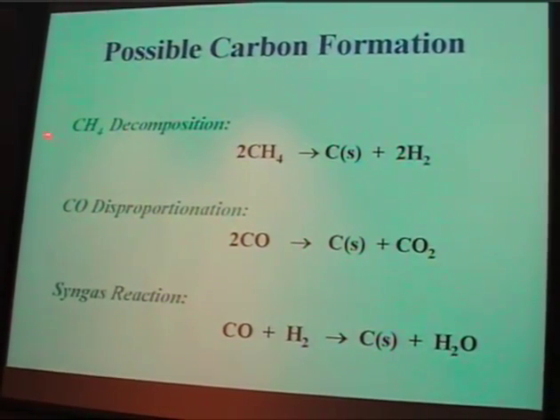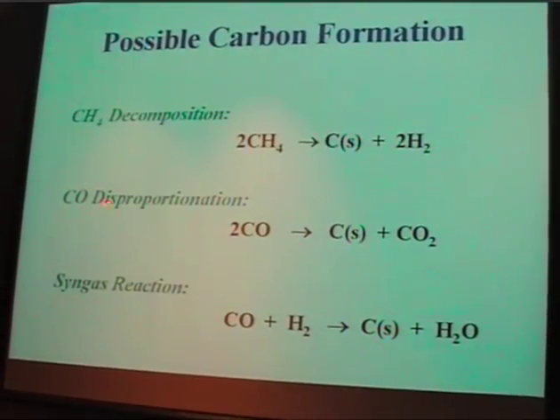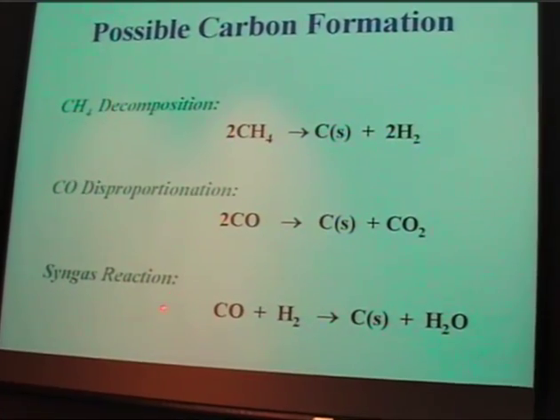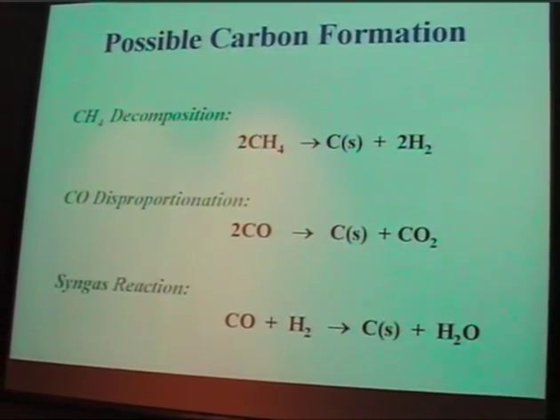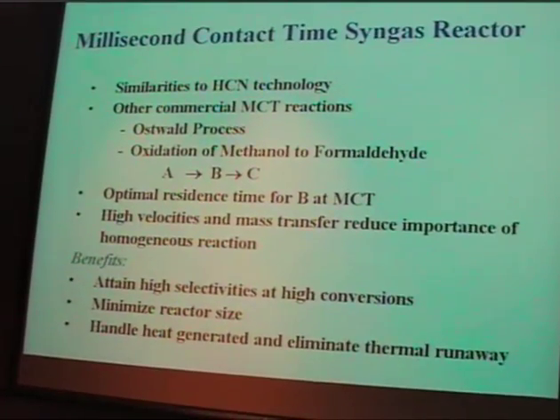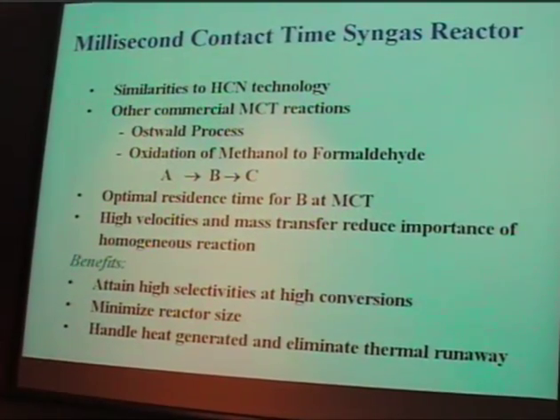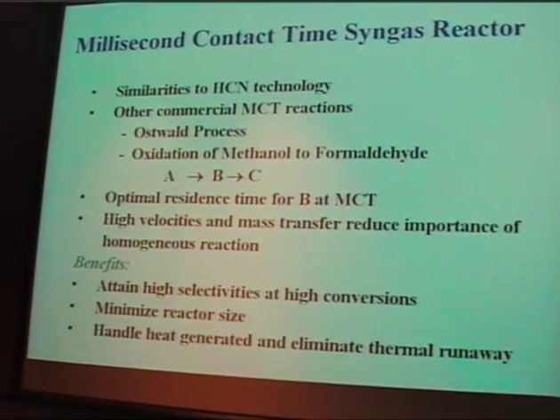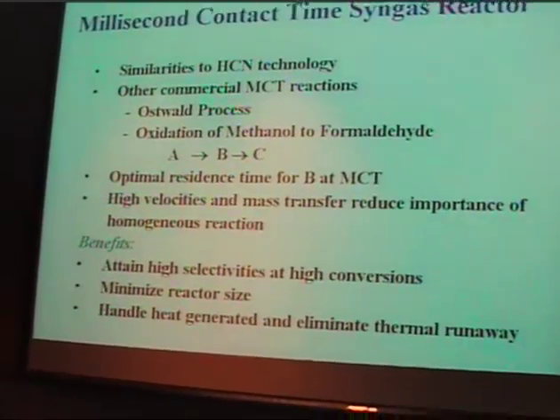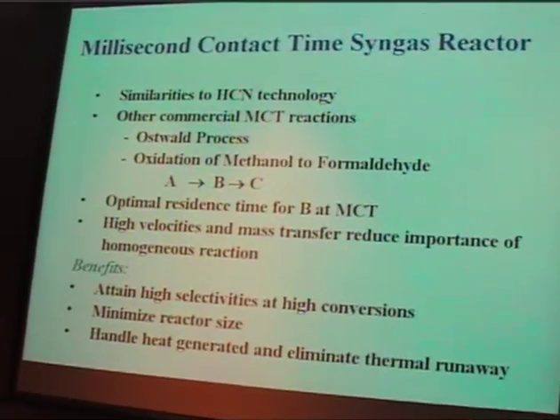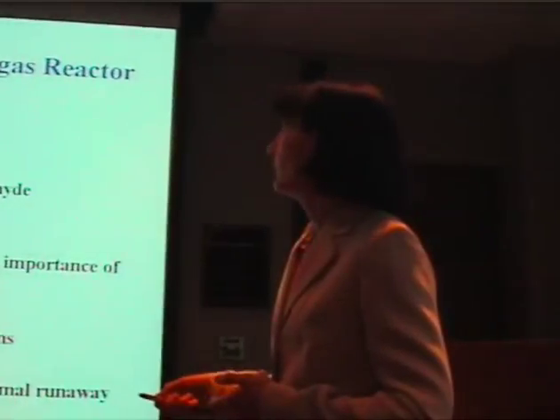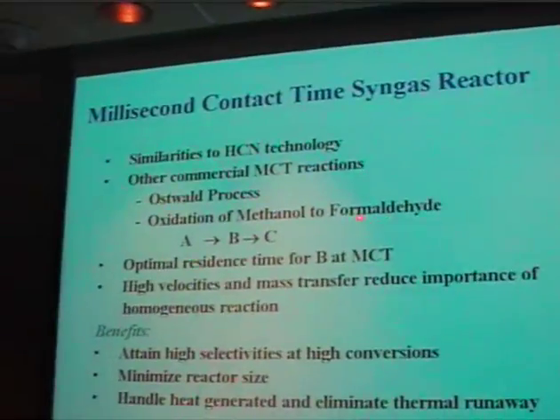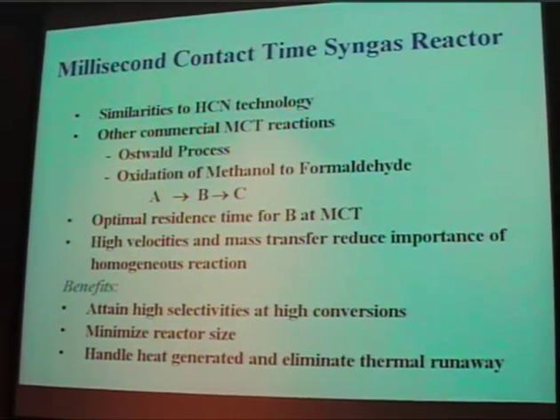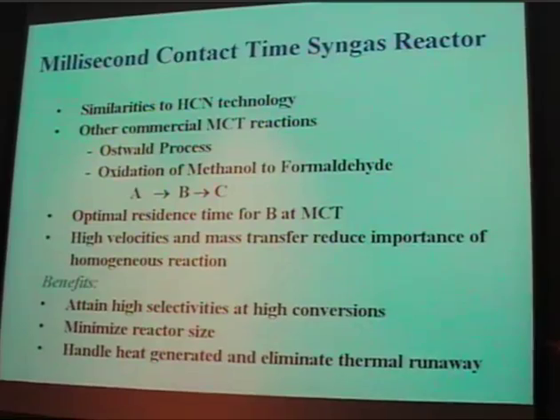And for carbon formation, that can occur due to the methane decomposition, the CO disproportionation, and the syngas reaction. So DuPont had a strong technology in HCN production. They're a major producer of that, so they had a lot of expertise in millisecond contact time, and they felt comfortable with this approach. And it's already known out in the technical world, the Ostwald process, nitric acid formation, converting methanol to formaldehyde.